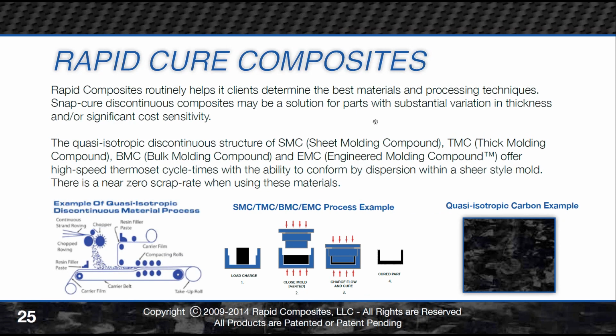So page 25 here, this talks about rapid cure composites. Now, these are going to be thermoset materials. Everything I showed you up until now has been thermoplastic. But I'm going to get into more details about this. A lot of people are familiar with SMC type materials, which stands for sheet molding compound. TMC is thick molding compound. BMC is bulk molding compound. And EMC is engineered molding compound. So the differences are fairly significant, but there is a common denominator amongst all of them in that they're quasi-isotropic and they're discontinuous. So they're basically a 3D oriented fiber.